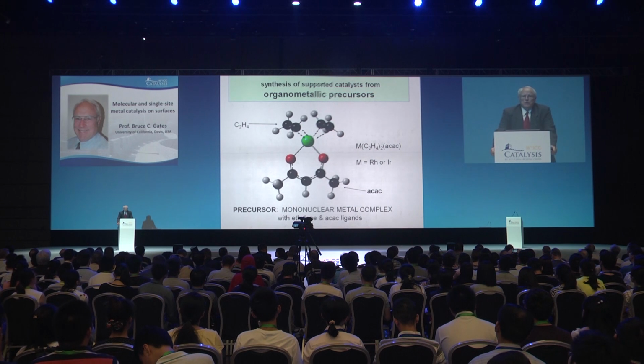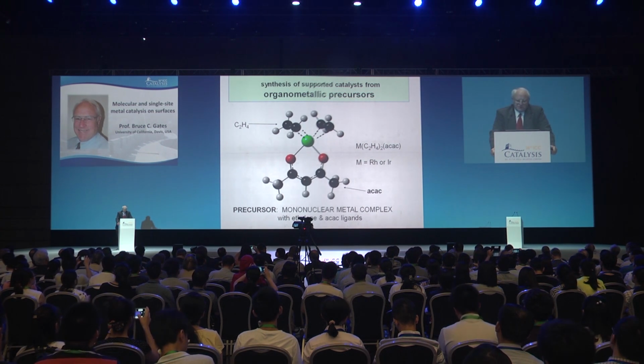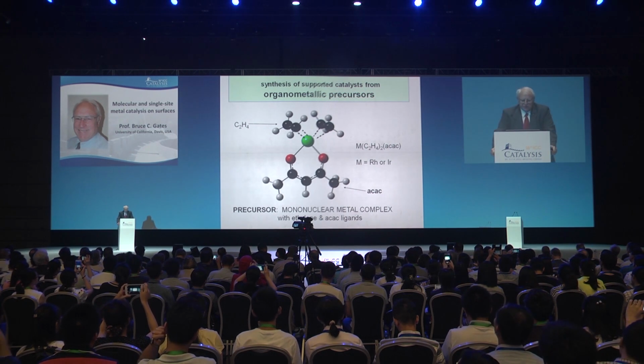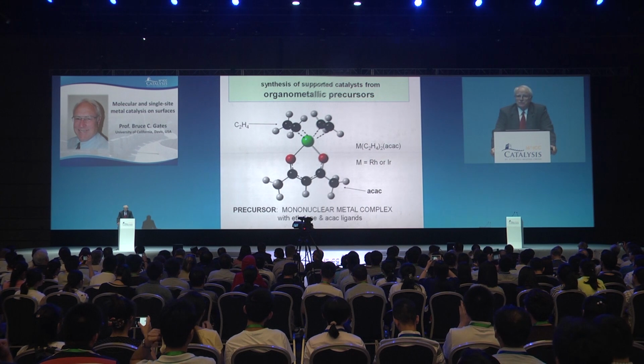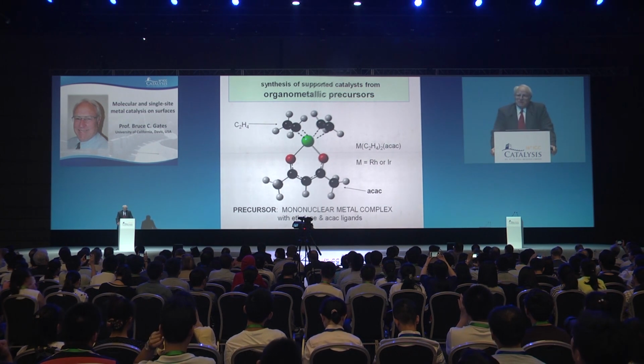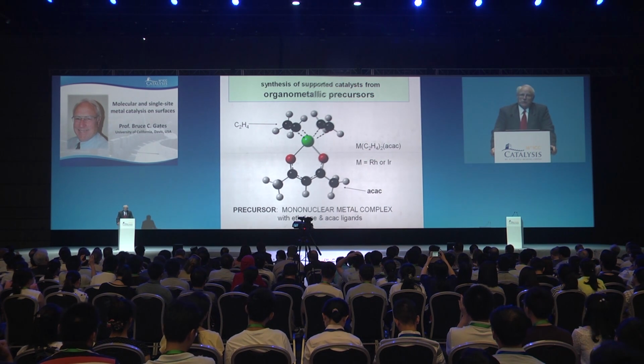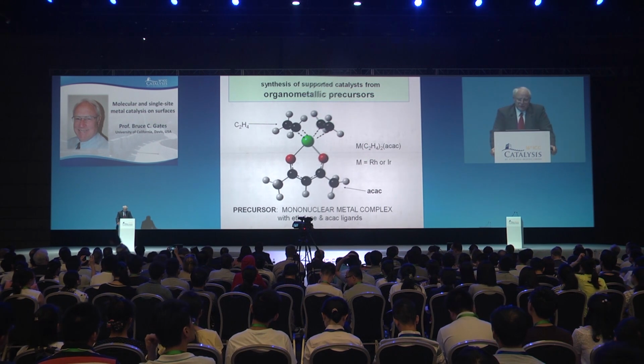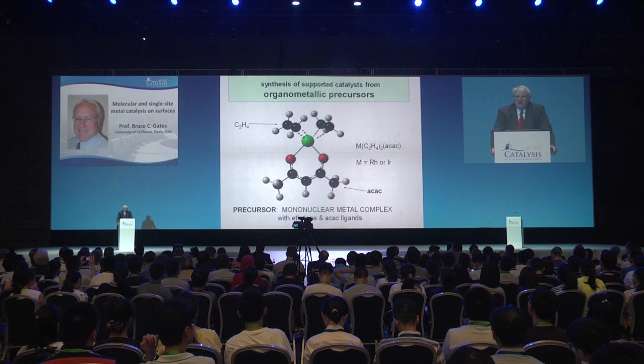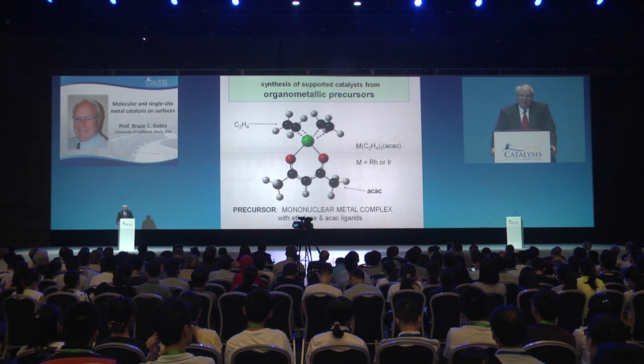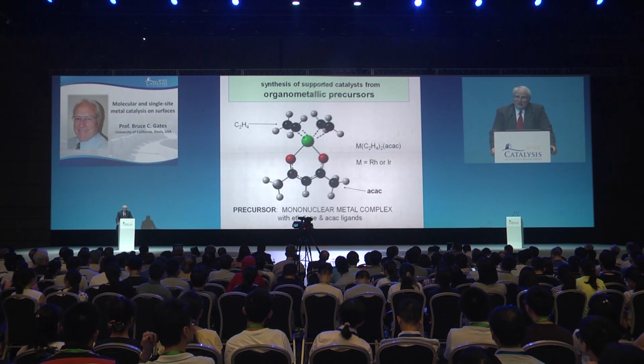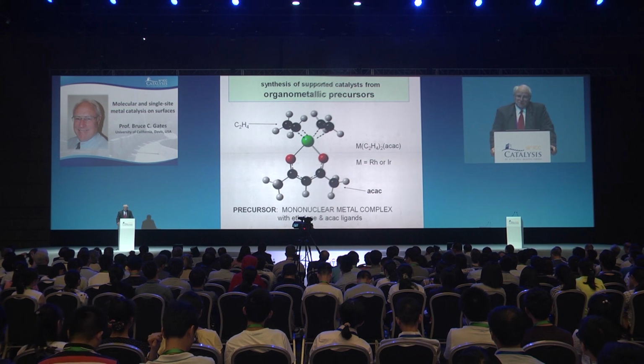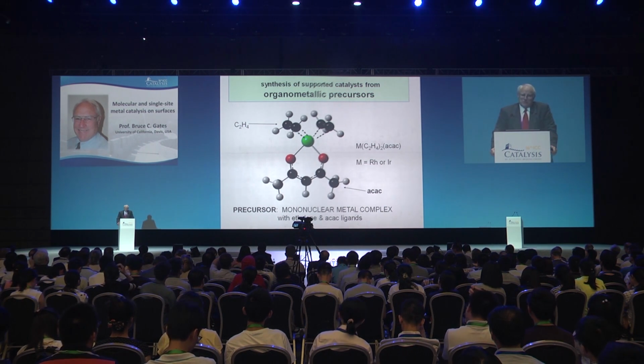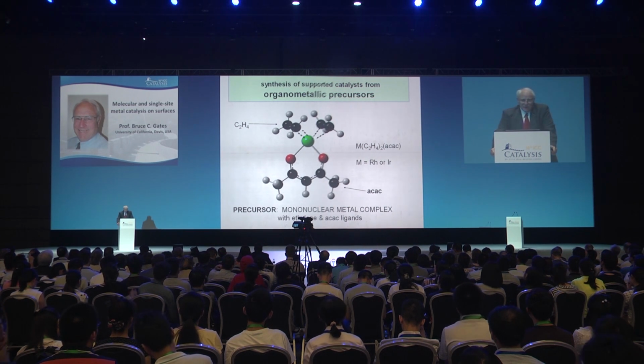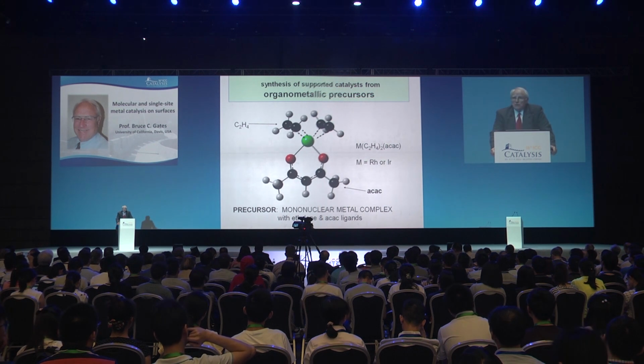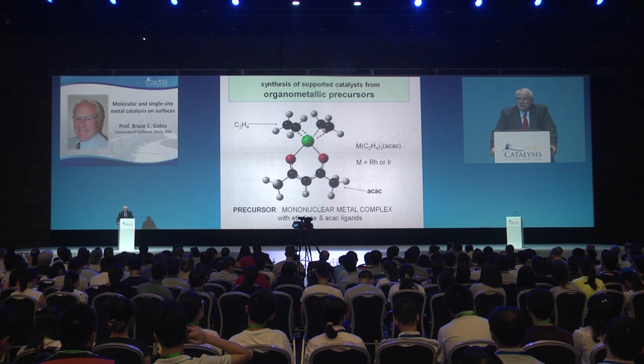So here's an example of a precursor molecule. We'll talk by example about this one where the green metal atom is iridium or rhodium. The groups bonded to this are ethylene ligands, pi-bonded ethylene—good ones because they're reactive. The other group bonded to the metal is ACAC, acetyl acetonate, and the red atoms are oxygen. That's a bidentate ligand in this precursor. What we're going to see is this precursor can react with OH groups on a number of surfaces, like oxides, making HACAC, and then bonding the metal to the surface of the support through two metal-oxygen bonds, just as you see in this precursor.